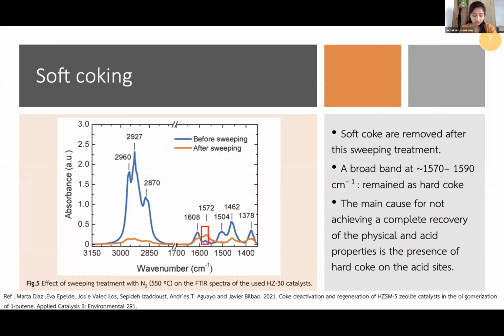For soft coke, a great amount of retained soft coke is removed after this sweeping treatment, which is evident by the decrease in the intensity of the absorption band. This observation reveals that the main cause of the catalytic deactivation observed in the early stage of the reaction is the confinement of soft coke.